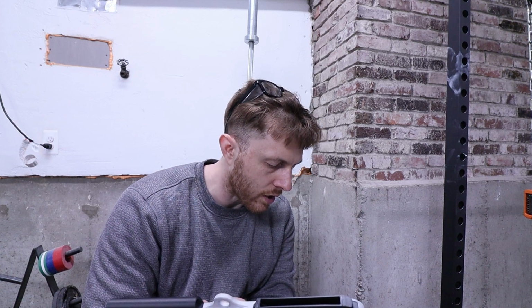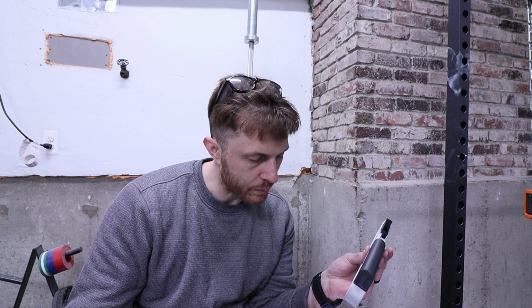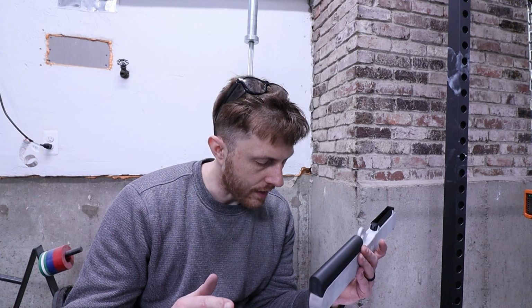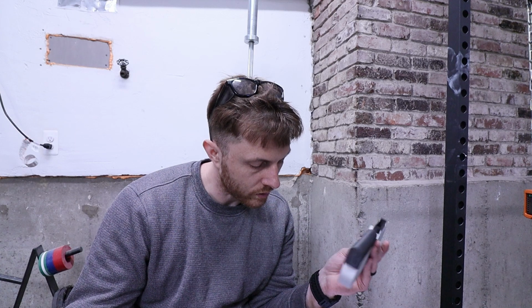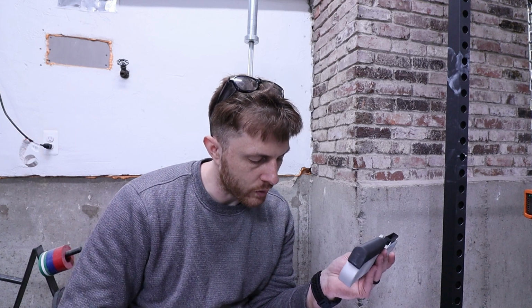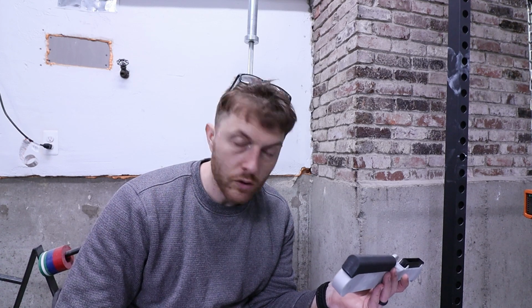It seems that the parameters are similar, and on some of these I actually did start writing my parameters on it. And for the glass filled ABS specifically, I wrote at least the amount of walls that I put. So I need to at least write the walls and the infill parameters and stuff on these. But regardless, it seems pretty similar to how I printed the PAHT, right? So I have a pretty good comparison here to two materials that I am using. And so for the horizontal orientation, I'm getting low to high 90s on the ABS glass filled, whereas on the high I was getting low 180s on the PAHT, twice as much.